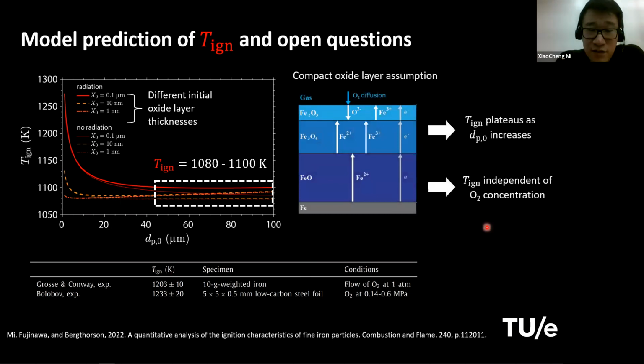But the two main assumptions we made in this kind of model come from metallurgy studies, and this gives us some unique features: this ignition temperature plateaus as the size of the particle keeps increasing for larger and larger particle size, and also this ignition temperature is independent of the oxygen concentration in the gas. This sounds counterintuitive, but the reason is that this very top layer of Fe2O3 can adapt its own growth rate to the oxygen concentration in the gas.